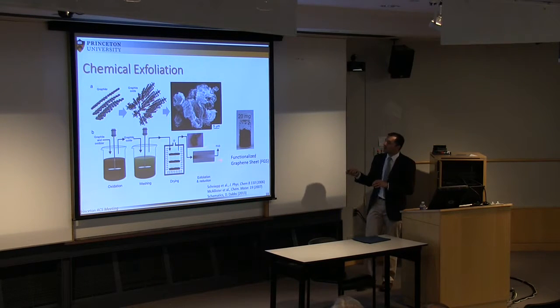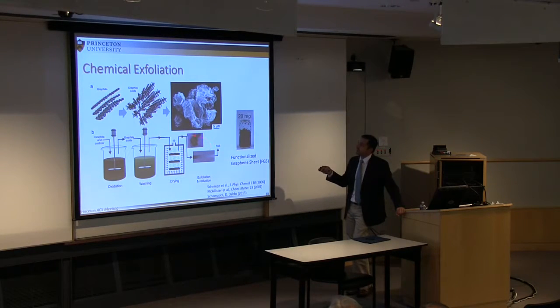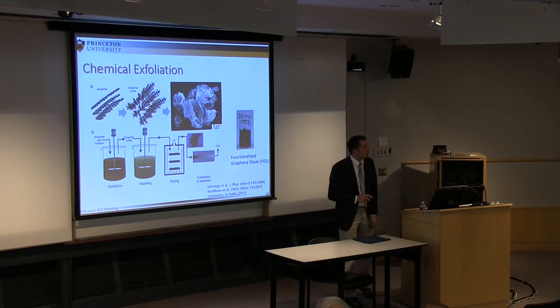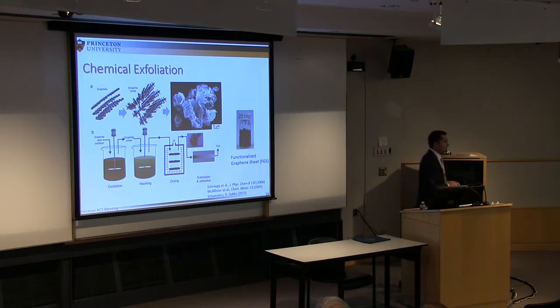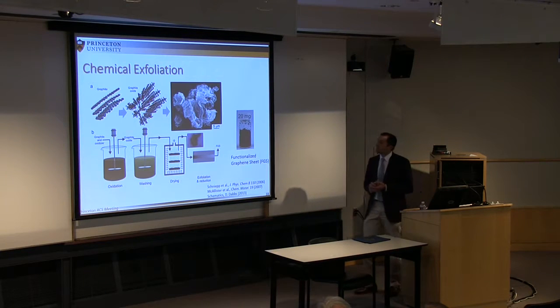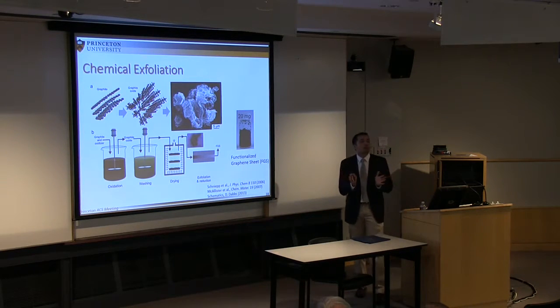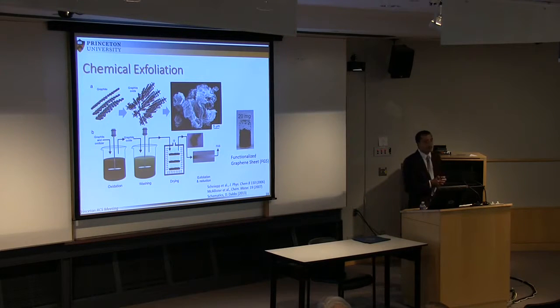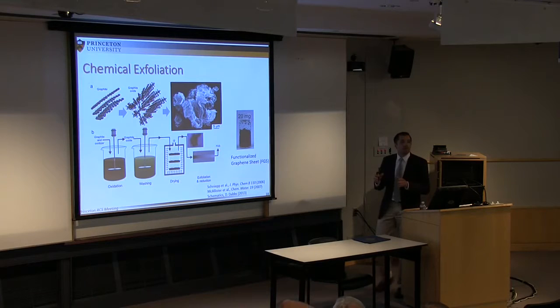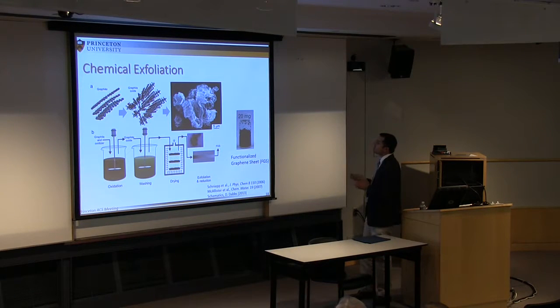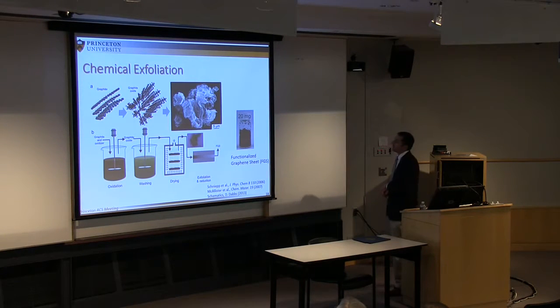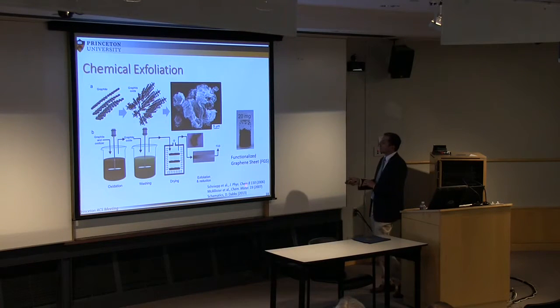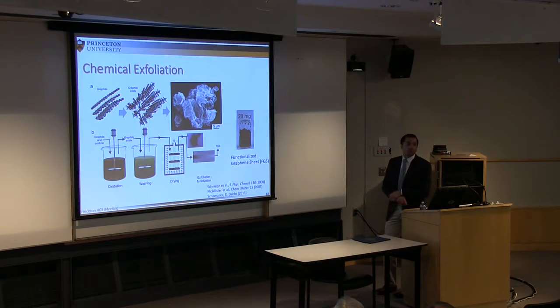And so my former group came up with this innovation. They heated this material. When you heat it under a protected atmosphere at about 1000 degrees C, ideally, you can effectively separate those graphene oxide sheets. And in the end, you have what we call functionalized graphene. So it looks like this. This is a 20 ml vial, which has the graphene powder. And this is an SEM image from the study back then in 2007 of crumpled graphene sheets.